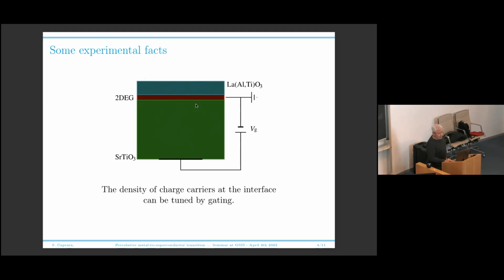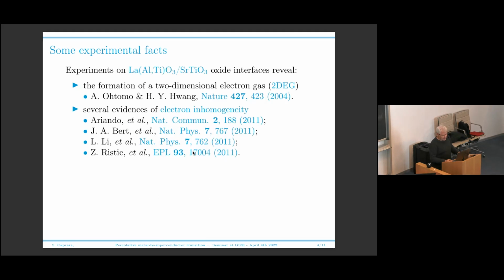And what is even more interesting is that you can gate the two-dimensional electron gas by standard gating. So you have a difference of potential between this far end of the strontium titanate and the two-dimensional electron gas. And you can vary the charge carrier density at the interface by simple gating. This is common in semiconductors. You can vary the carrier density in semiconductors by gating. What is striking of these systems is that there are several evidences of electron inhomogeneity.